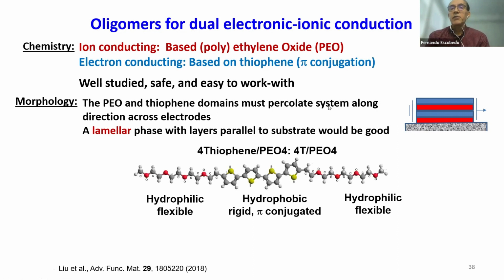And so we came up with the idea of synthesizing or studying the system that, as you can see, is like a small tri-block. In the middle, you have these hydrophobic pi-conjugated rings of thiophene. In this case, we have 4 of them. And on the sides, we have these short chains of PEO. So in fact, we use basically 4 ethylene oxide units on either side and 4 thiophene units in the middle, with the expectation that they will form something like a lamellar phase, and we can have these different domains for different kinds of conduction.